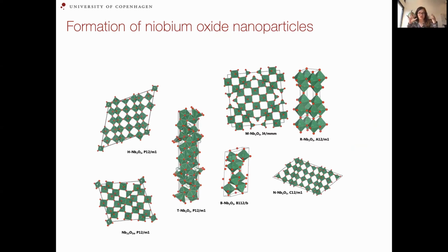So again, just like tungsten oxide, niobium oxide has a ton of different polymorphs. These are some of the ones, and just a fraction really, of niobium oxides that are reported in databases. Niobium oxides have been receiving a ton of attention recently, because it's been discovered that they are very, very good for high rate lithium-ion batteries. So you can get a lot of lithium in very quickly. But again, here we have a lack of understanding of how we can form a specific polymorph, and actually also of the structures of them.